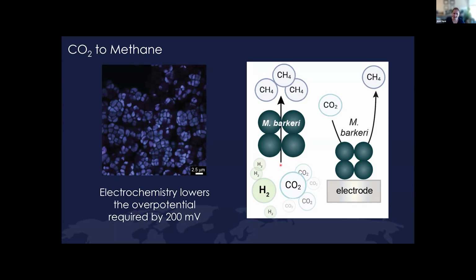Conventionally, these microbes take hydrogen and carbon dioxide and turn it into methane. The problem is this hydrogen is very energy intensive to produce and can be very precious. So what we've been able to do is swap out this hydrogen for an electrode and see that these microbes, especially when they're coated and protected, convert this carbon dioxide to methane with very high efficiency, at about 30% lower energy than is required to generate hydrogen for the conventional approach.